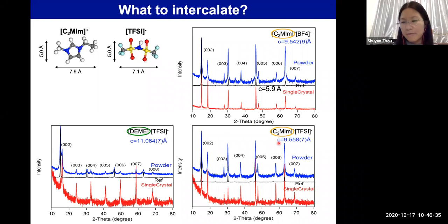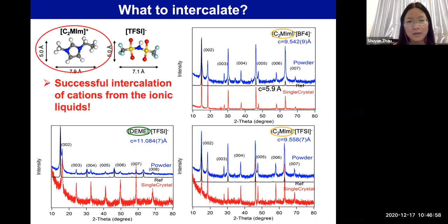And to further confirm this, we compare this intercalation using another ionic liquid with a different cation but the same anion. And now we can see that when we change the cations, the interlayer spacing also changes. So this control experiment tells us that here we have successfully intercalated the cations from the ionic liquids.